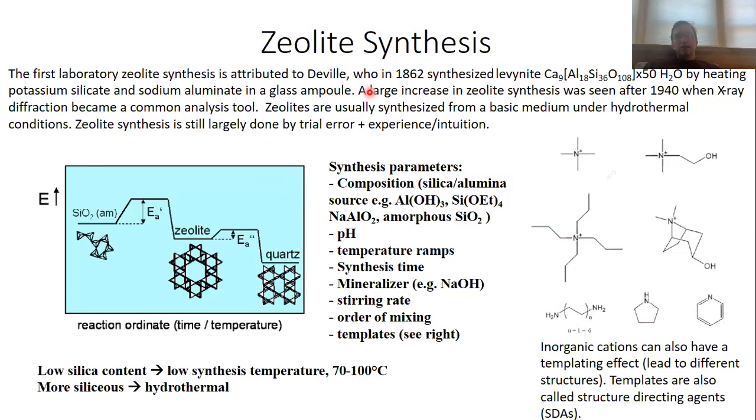But a large increase in zeolite synthesis was only seen when X-ray diffraction became a common characterization tool. These zeolite structures are fairly complicated. They have large unit cells, and therefore they could only be well characterized after X-ray diffraction was invented. Typically, zeolites are synthesized under hydrothermal conditions in a basic medium.